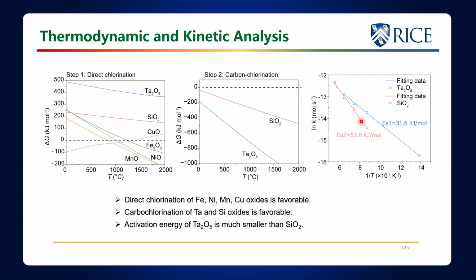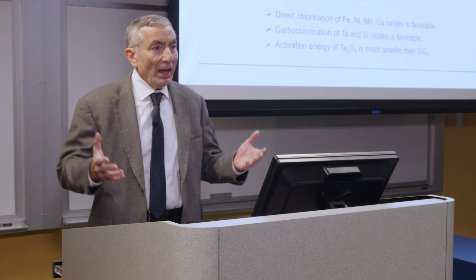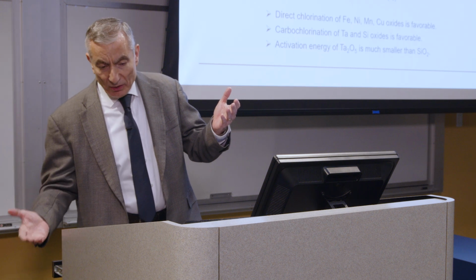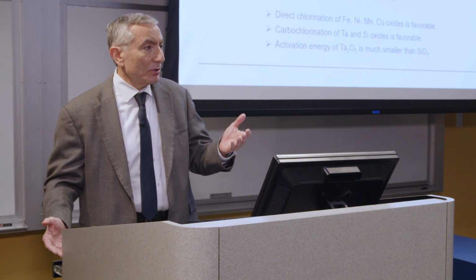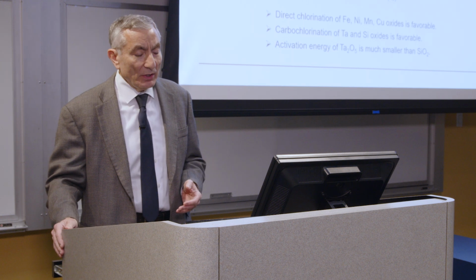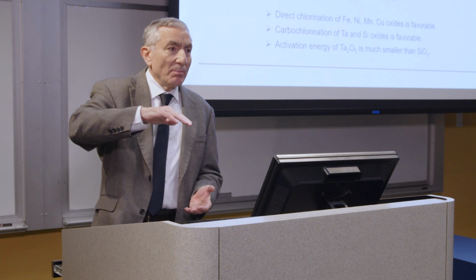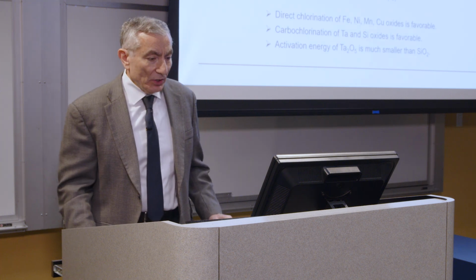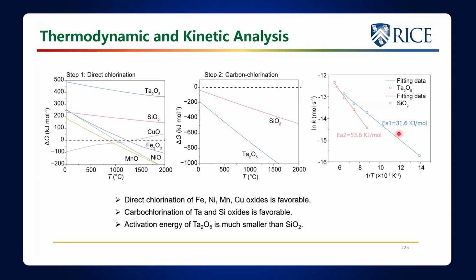It turns out the activation energy to get silicon to react, although thermodynamically it's favorable, meaning that the product is more stable than the starting material, is the thing to look at. It is thermodynamically driven, but you have to look at how high the barrier is to go over. This is 53 kilojoules per mole for silicon, 31 kilojoules per mole for tantalum. So we should be able to hit this barrier before this one ever activates. And so we'll be able to separate out the tantalum from the silicon, because the activation energy to make the chloride from the carbochlorination is in our favor.